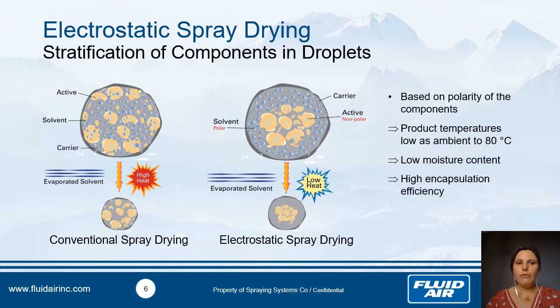If you have different compounds inside, we can take the case of an emulsion where you want to dry oil. Your active is oil, and you have a carrier with water. In the conventional spray dryer, when you evaporate water with high energy and heating, you will have a homogeneous repartition of your oil and your carrier. That means you have oil at the surface, and this oil could be damaged by oxygen, and in the case of essential oil it will also evaporate during storage.